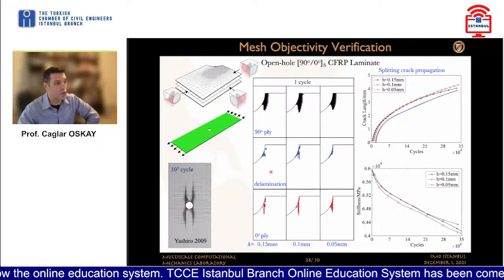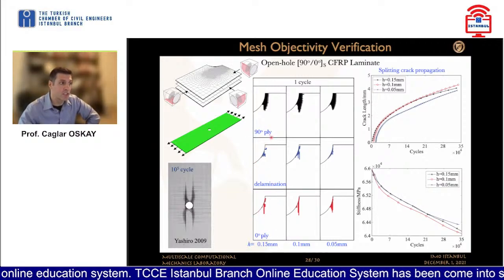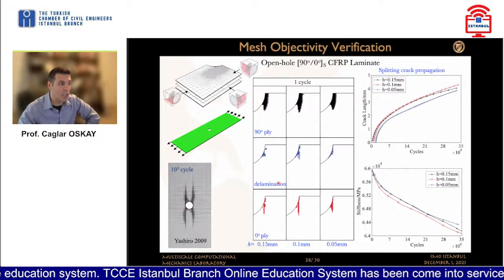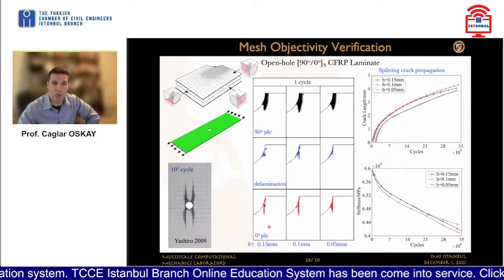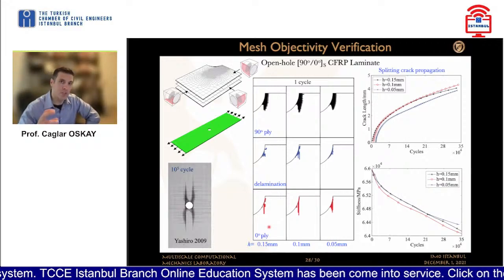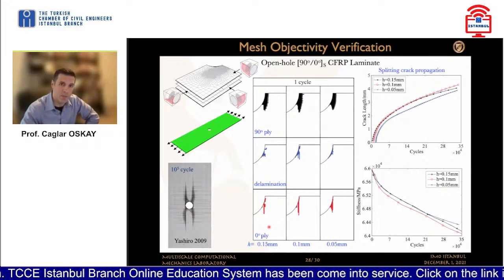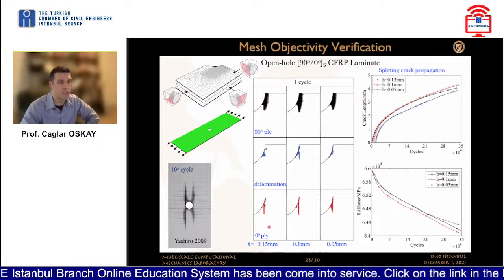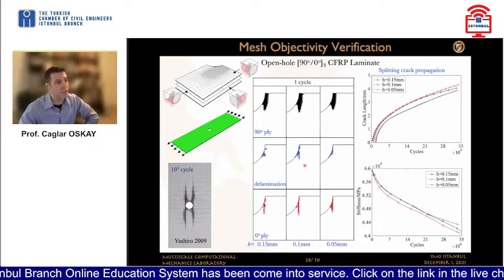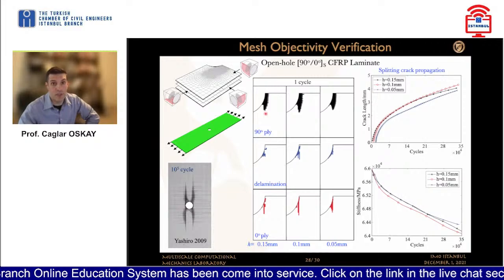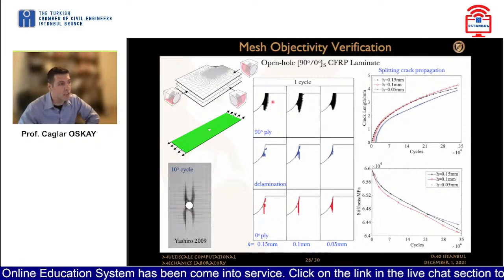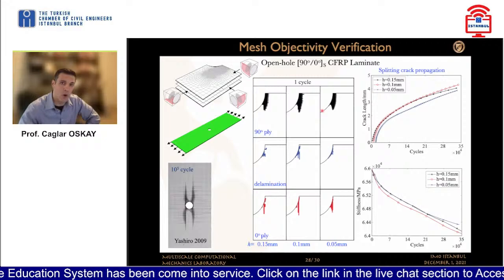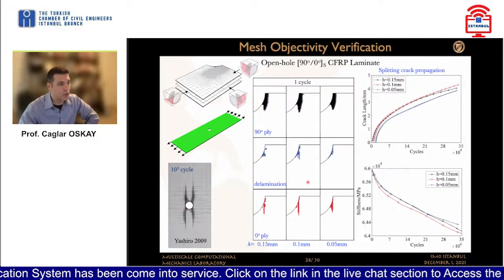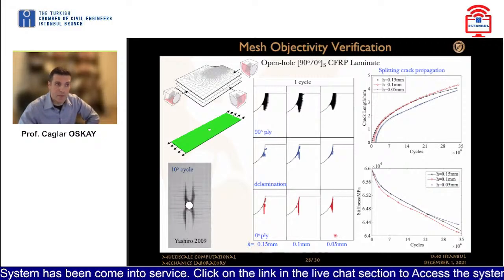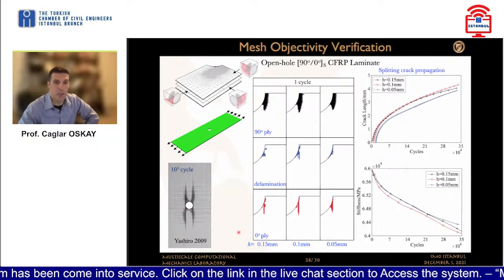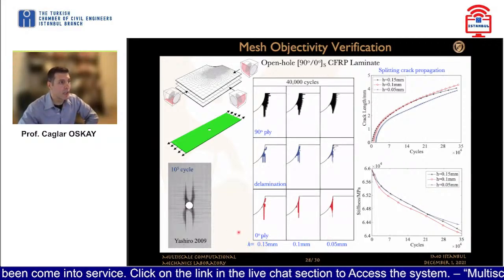And we're tracking three different failure patterns: the 90-degree ply damage, delaminations, as well as the matrix damage in the 0-degree ply. Because the fibers are so much stronger, you don't see much of a fiber failure in these simulations. But because of the 90-degree, 95% of the ultimate stress is already imparted on the first cycle, you see quite a bit of damage developing already. But after that, what we're going to show is how the damage evolves under this loading condition as a function of load cycles. And this is how it shows.